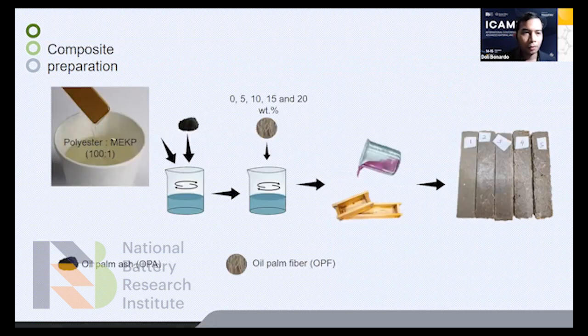For preparation of the composite, polyester and MEKP with a ratio of 100 to 1 resin to hardener were mixed in a container and stirred manually for 1 hour at room temperature until the resin solution was mixed. Next, OPA is added to the matrix by manual stirring to improve the bonding characteristic of the fiber. Oil palm fiber at 0, 5, 10, 15, and 20 weight percent loading was properly mixed with the polyester matrix using a hand stirrer and gradually poured into a wooden mold of dimension 300 millimeters, 300 millimeters, and 10 millimeters.